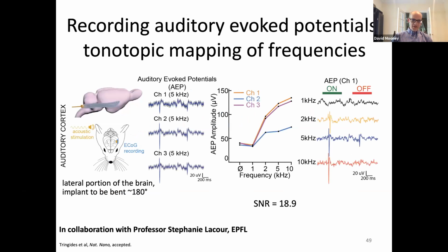We can do this in a variety of settings. So for example, in this case, we're also looking at using it in the brain, where we're looking to be able to record signaling due to acoustic input. In this case, we're placing it in the lateral part of the brain, which required it to be bent 180 degrees. And you can appreciate that when we input the noise, we get a good recording from our array indicating we are able to monitor the electrical activity. And this work is all done in collaboration with Professor Stephanie LaCour at EPFL.